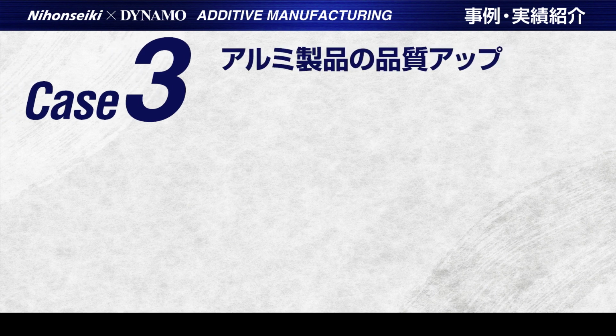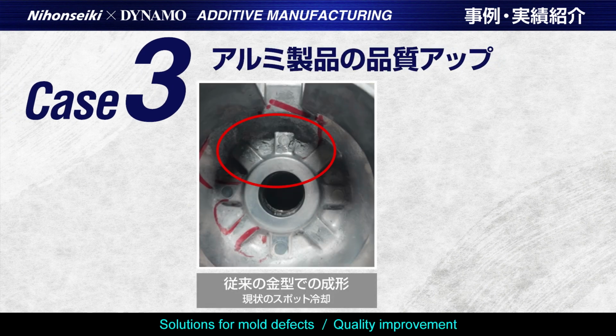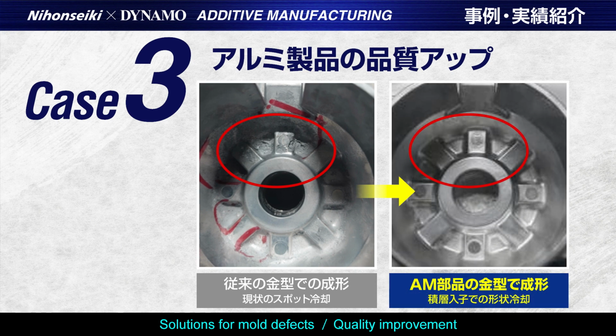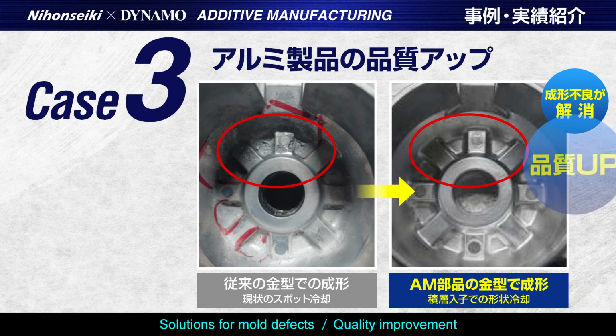Case 3. Same as Case 2, measures against seizure. This is a mold using conventional drilled spot cooling. This time we tried conformal cooling solutions for the burned area. Conventionally, burning occurred at the initial stages, but as you can see, there is no surface deformation and the surface is left very smooth.